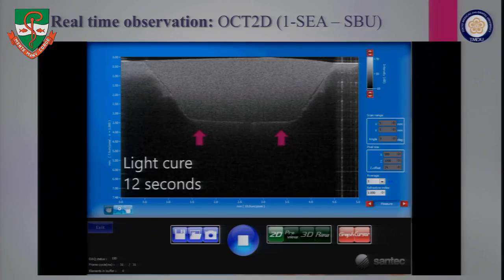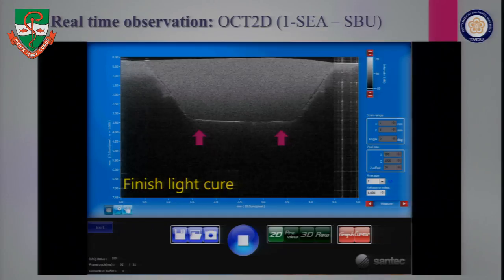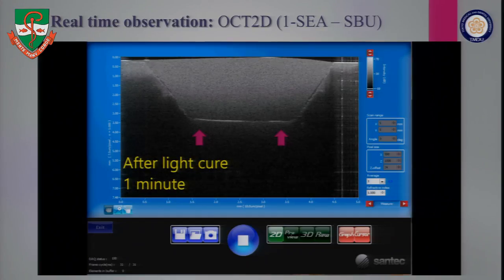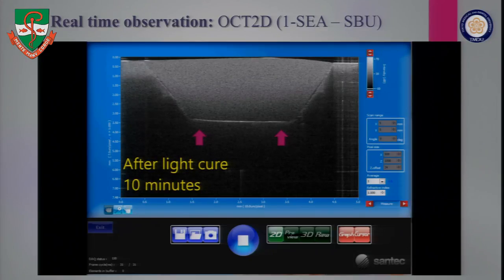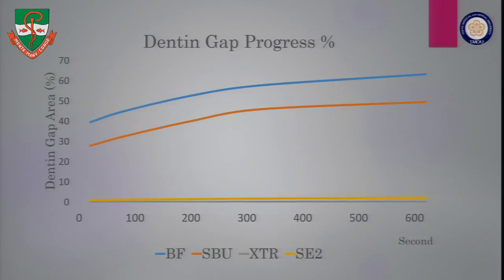Look at this part carefully. Now you see the white line indicating the gap formation during the light curing. Then even after the light curing, the gap still extended because of the residual stress in the composite. Okay, that's why we evaluated the gap afterwards.